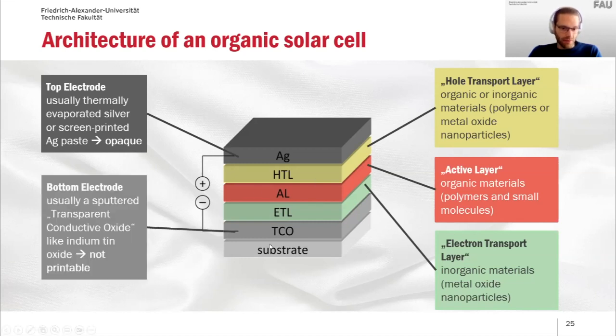Then on the other side, the front electrode or bottom electrode is usually a TCO, a transparent conductive oxide, like ITO, indium tin oxide. And this material obviously needs to be transparent because that's where the light comes from into the solar cell. So this needs to be highly transmissive. The drawback for the standard materials is that they are sputtered and because of this, not solution processable, printable.